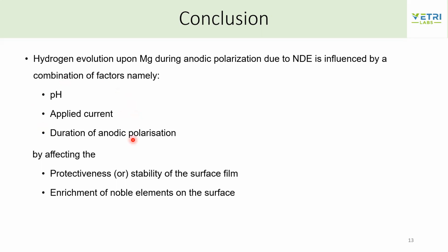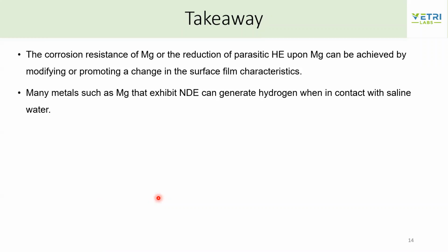So how do these factors really impact? They affect the stability of the surface film, and they also lead to excessive dissolution, which causes enrichment of noble elements, which in turn support the hydrogen evolution.